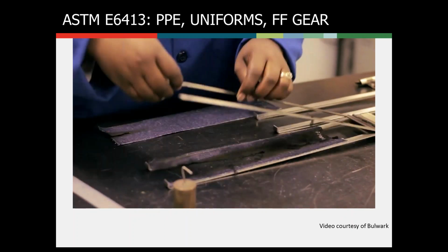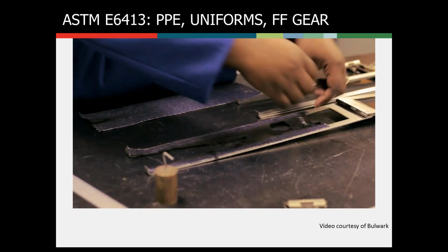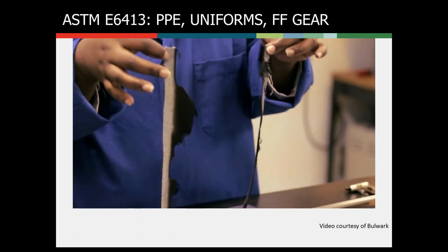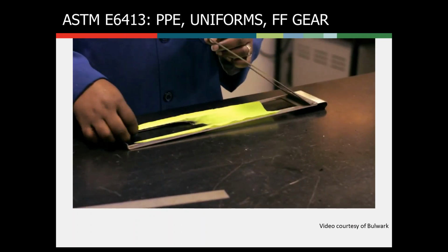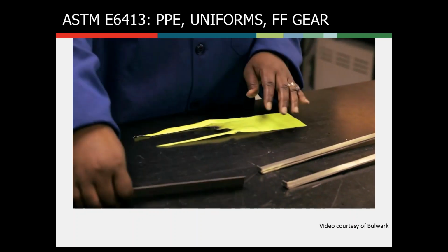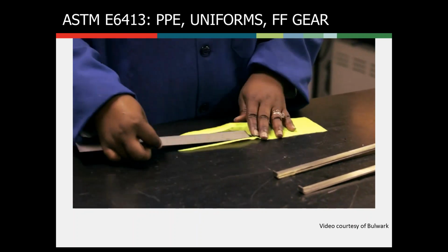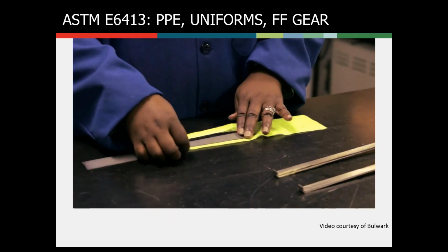Difficult to even measure the char length there. On the non-FR denim, you've essentially consumed the entire specimen. As you see, she can rip it in half. And then in the middle ground, you've got the char length here for the last material. Different test methods and different test standards are going to require char lengths of less than 4 inches or less than 6 inches, depending on what you have. It all depends on which standard is requiring you to run that test.